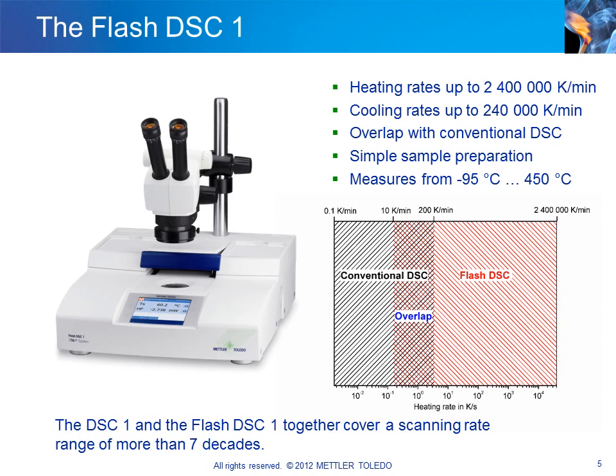The Flash DSC-1 provides heating rates of up to 40,000 degrees per second, that is 2,400,000 degrees per minute, and cooling rates of up to 4,000 degrees per second, or 240,000 degrees per minute. This means that the Flash DSC-1 allows measurements to be performed over a scanning rate range of 4 to 5 decades. The Flash DSC-1 and the DSC-1 together cover a scanning range of more than 7 decades. The temperature range of the Flash DSC-1 is from minus 95 degrees Celsius to plus 450 degrees Celsius. Cooling is provided by an optional intracooler.